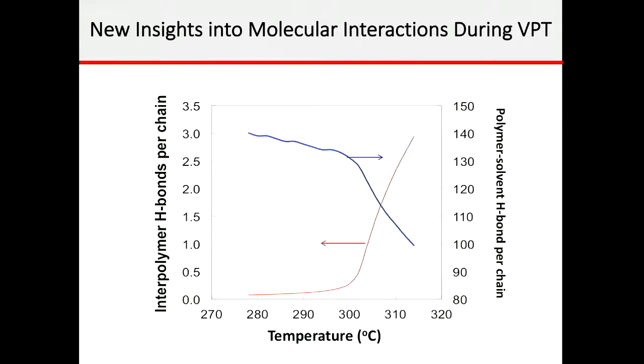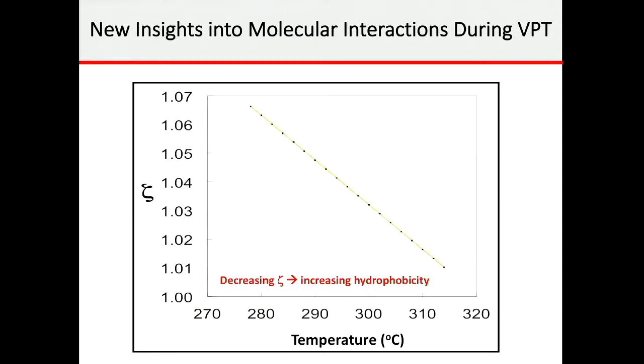And we got, of course, interesting insights. For example, at the transition temperature, we found that the interpolymer hydrogen bonds per chain decrease abruptly, whereas the polymer-solvent hydrogen bonds per chain increase abruptly. The interesting part was our finding that this interaction parameter, zeta, had to have temperature dependence, and particularly a decreasing zeta with increasing temperature implied increasing hydrophobicity.